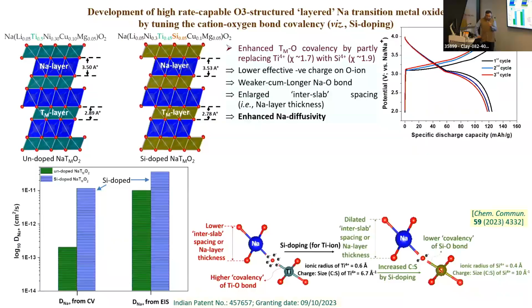Now, one thing which must have come to the mind of all of you is that the way I'm improving the air water stability is by making it more difficult for the sodium ions to spontaneously come out of the lattice, which means I am suppressing to some extent the sodium transport, making it less facile. I'm lowering the kinetics. So that should negatively affect my rate capability. And that is indeed so. Just that the rate capability is not very badly affected by slight alteration of the charge to size ratio. Rather, it is the spontaneous sodium extraction which is more drastically affected. But having said that, I don't want to compromise on my rate capability as well.